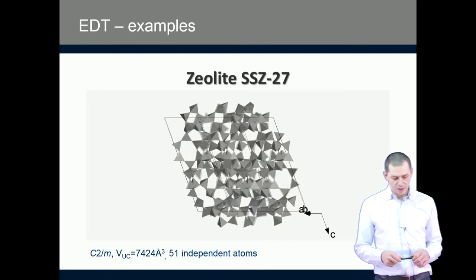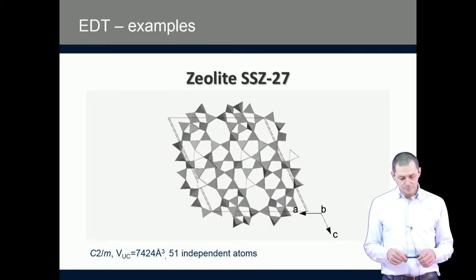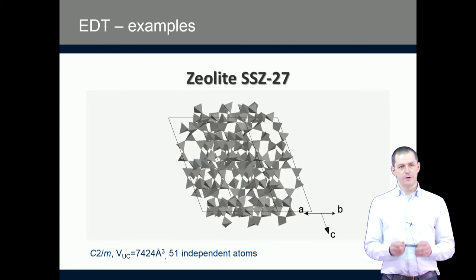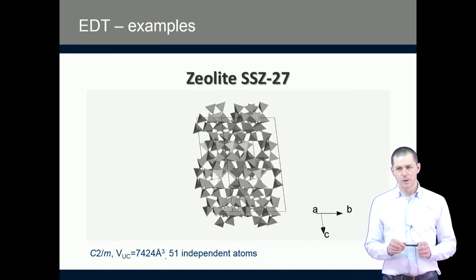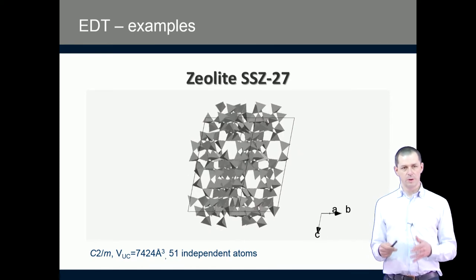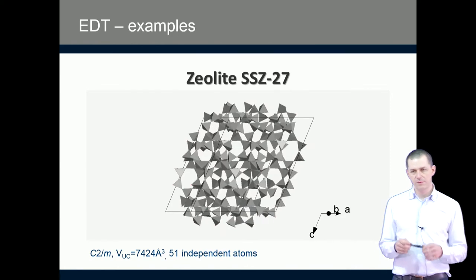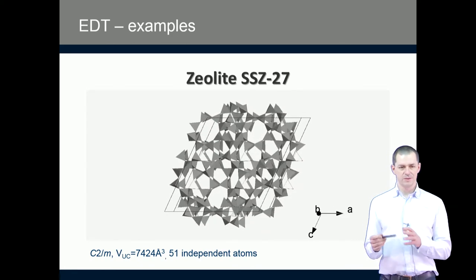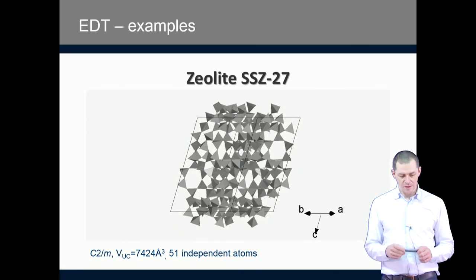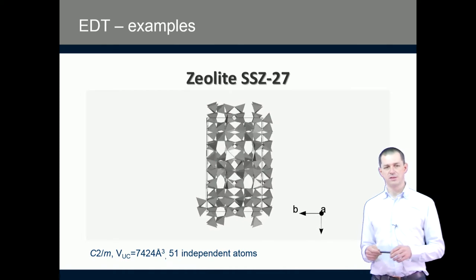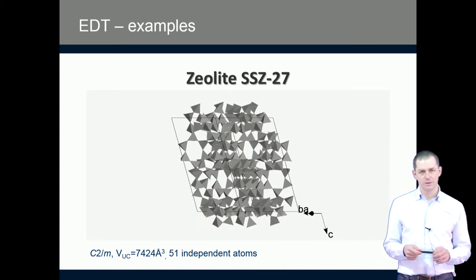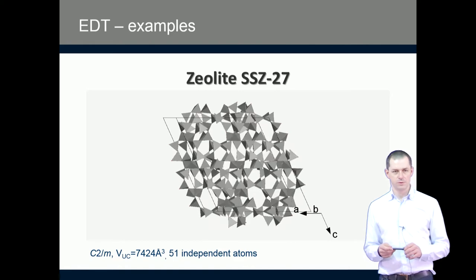So now, if the material is well crystalline, so if there is no problem with the crystallinity of the material, and if it is stable or at least reasonably stable in the beam, then there is a very high chance that we can analyze and determine the structure from electron diffraction data.